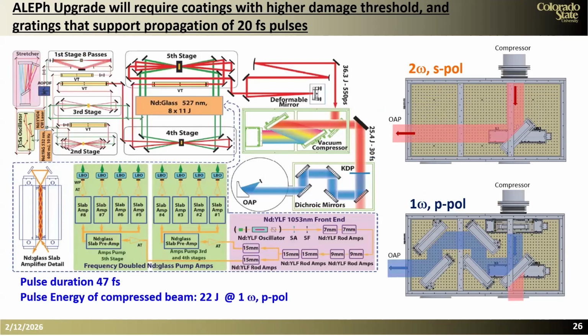Now, what are we doing, for example, to help advance the upgrade of the Aleph laser? This is the architecture of the Aleph laser. This is a titanium sapphire laser, and it is pumped by frequency-doubled green light from neodymium glass amplifiers. What you see here is that the laser beam is amplified, goes into a compressor, and then from the compressor it goes into two chambers where you do experiments. At a certain point it is frequency doubled, but nevertheless, one critical component of this laser is the compressor. So we are working, number one, on coatings that will have a higher damage threshold at ultrashort pulse duration, and on dielectric gratings that will also have a very high damage threshold.